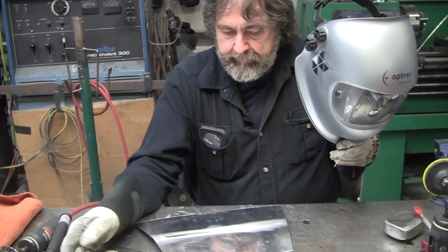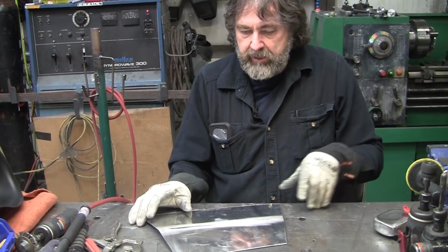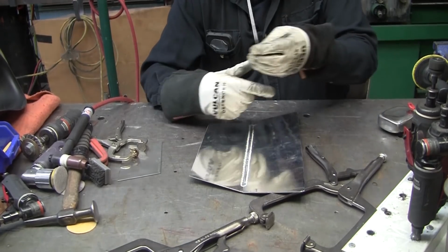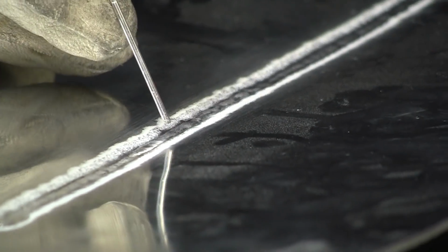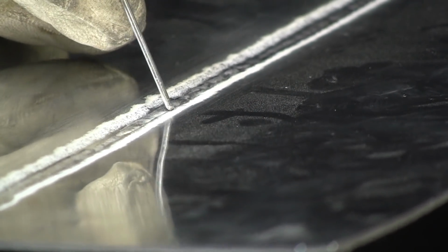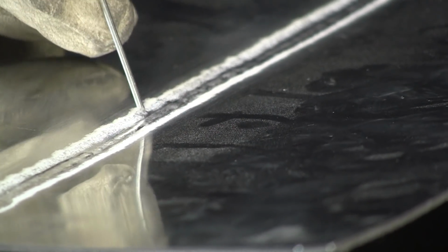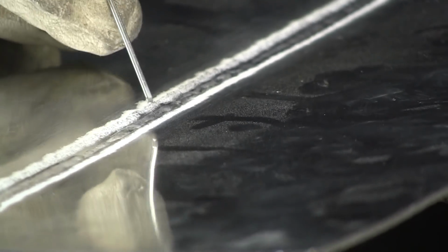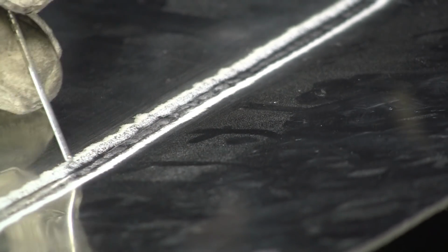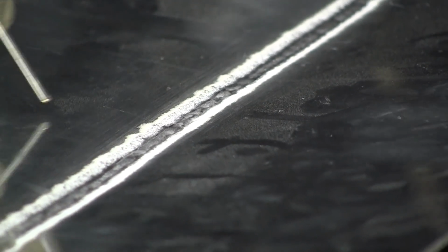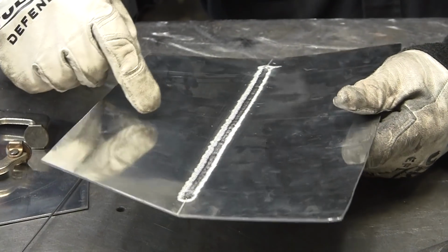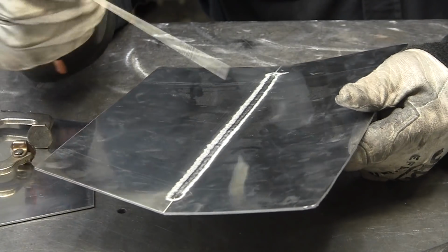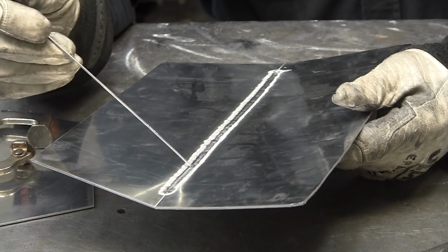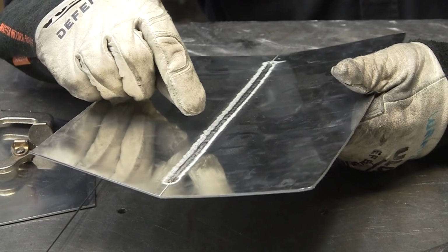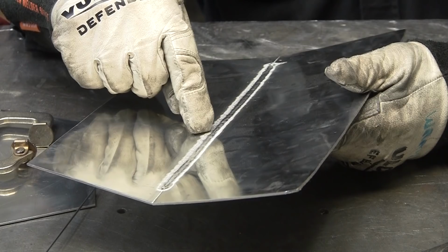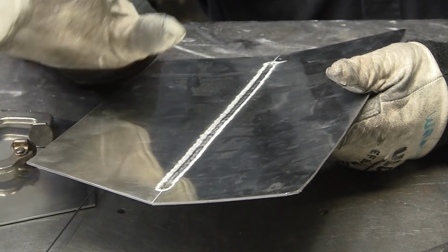But with fusion welding, there can be a lot of problems. Like for instance, in the video last night where I fusion welded that aluminum, you'll see this situation here where we have this lot of drop through on the edge here. When I ground it, and after I hammered it, there was a little tiny valley right on either side. And when we torture tested it, that valley, which has nothing to do with the welding, was just the fact that it's created by the drop through. If I had ground it instead of hammering it, or ground it first, that valley wouldn't have been created. It's just the condition of if you take an awl and scratch aluminum, that's always where the crack will develop. So because I had that little valley on either side of the weld, you'll notice after I hammered it with the ball peen hammer as hard as I could about 10 times in that last video, it fractured there. It was a fatigue fracture. It was nothing to do with the weld. The weld was as strong as the parent metal.